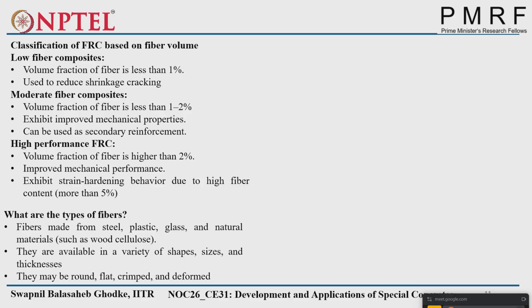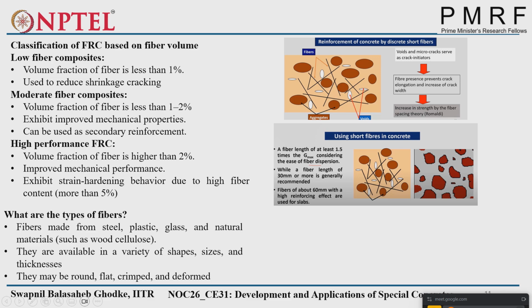So what are the types of fibers? Steel, plastic, glass, and other natural materials such as wood and cellulose. They are available in a variety of shapes, sizes, and thicknesses. They may be round, flat, crimped, and deformed. See, these are the concrete aggregates. Suppose these are the voids, and these are the fibers. You see, these are randomly oriented, right? So voids and microcracks serve as crack initiators. That's why we have to be careful about the amount of voids. The less the amount of voids, the less the possibility of having microcracks or crack initiators.